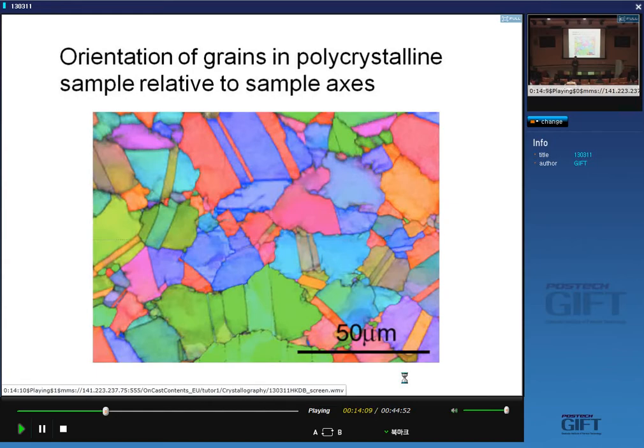Does anybody know one method of producing a random distribution of crystals? Given that you can't deform, you can't cast, because in casting you have preferred growth directions, powder metallurgy. So you make a powder and then you fuse, you join the powder together. If you do too much joining, you will get texture once again. Okay? Texture means a non-random distribution of crystals.